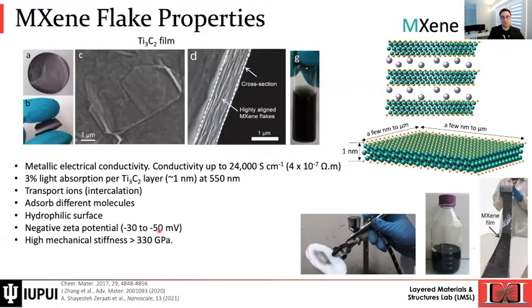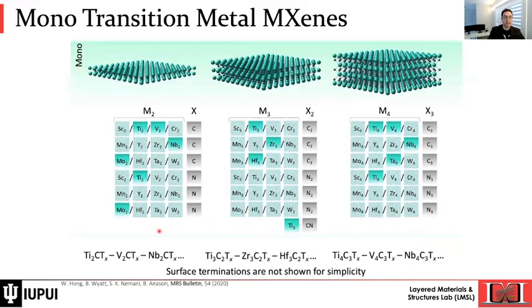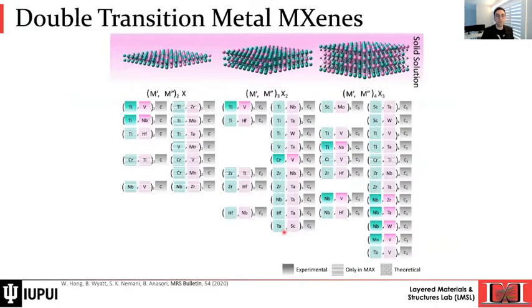Now, MXenes are not just Ti3C2. They can have a variety of compositions. For example, we can have vanadium carbide and niobium carbide, which is important when we're talking about tuning the mechanical properties. So that's why I'm mentioning the different compositions here. Also, we can have two different transition metals, which we call double transition metal MXenes. We have two, for example titanium and vanadium, mixed together in the form of a solid solution. So we can have different solid solutions: titanium vanadium in a 3-layer, or titanium vanadium carbide in a 2-layer, or titanium niobium in a 4-layer, and so forth.